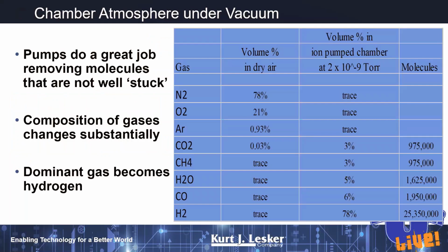Now, as I mentioned, at atmosphere we're sort of 80-20 oxygen, nitrogen, a little bit of argon. As we go down in pressure into the ultra high vacuum, those gases are gone. They're out of our system completely. And so we may still have something like 32 million molecules per cc left. We've still got some CO2, some methane, some carbon monoxide. But now notice that the big gorilla in the room, once we get into ultra high vacuum, is hydrogen. Hydrogen's incredibly tough to pump. It's a really sticky molecule.